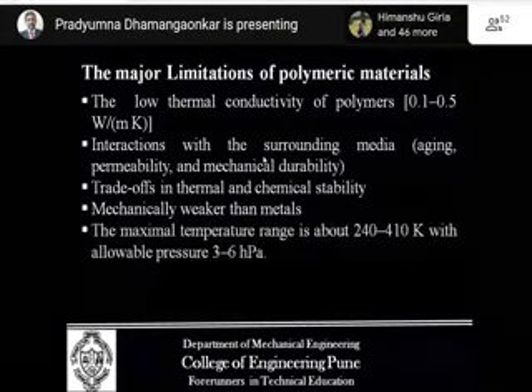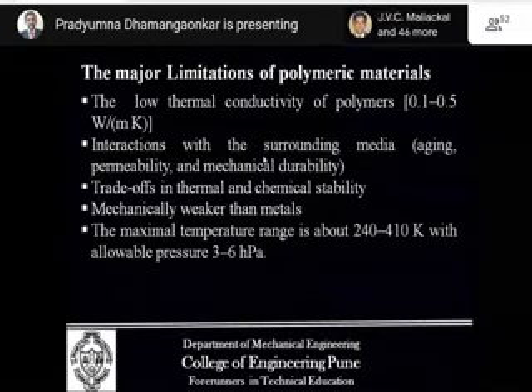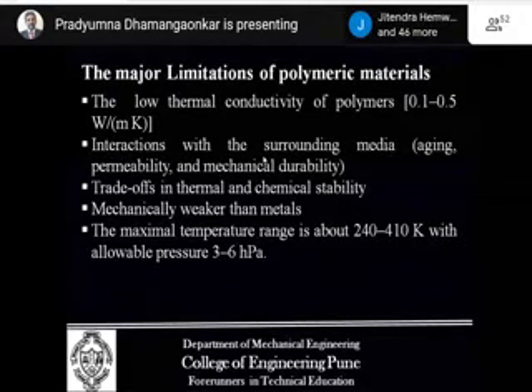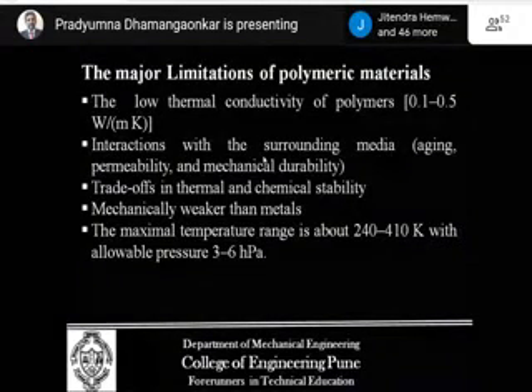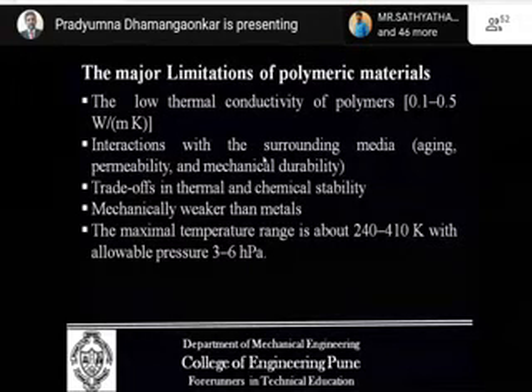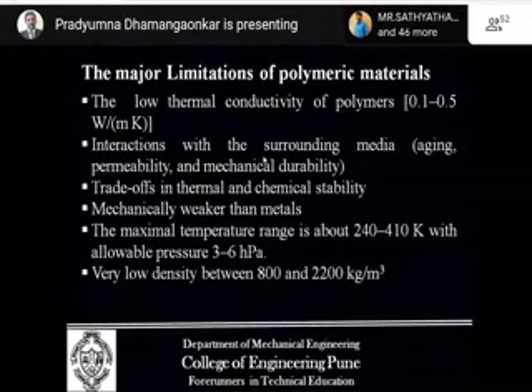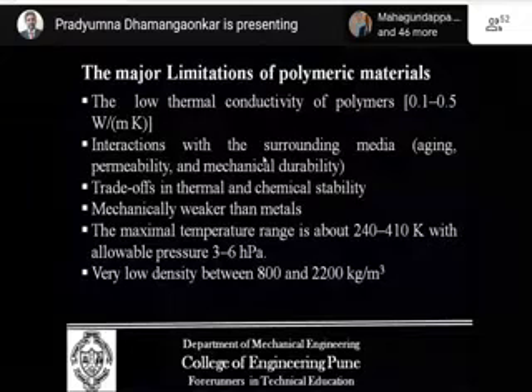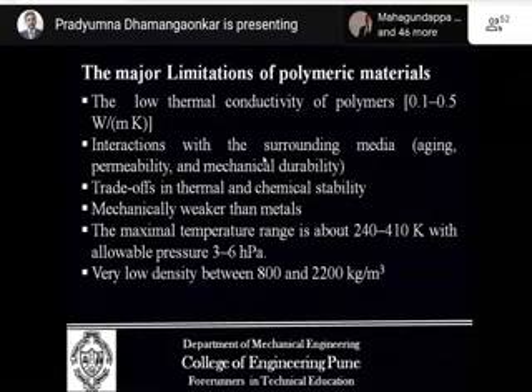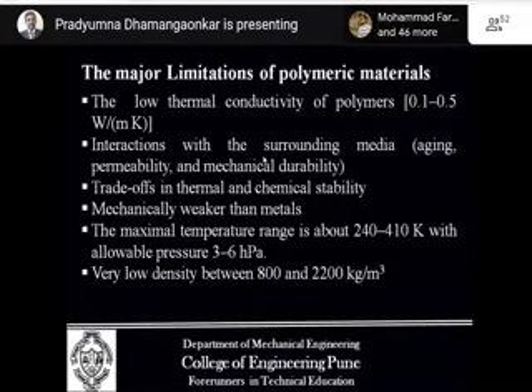The maximum temperature range is about 240 to 410 Kelvin. The allowable pressure is 3 to 6 hectopascals. It has a very low density between 800 to 2200 kg per meter cube. Most of the materials, their density ranges from 24 kg per meter cube to sometimes 9000 kg per meter cube.